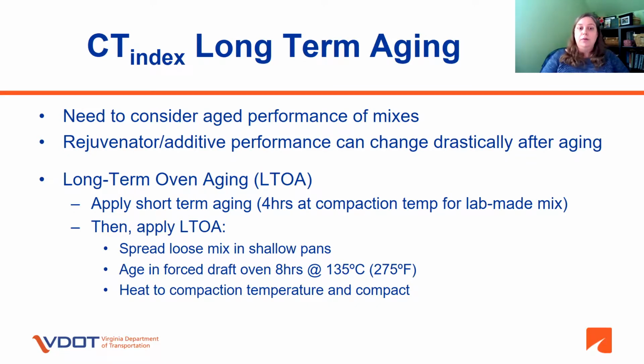After aging, rejuvenators and additives may significantly change your performance, and not in a good way. If a rejuvenator is not designed such that it continues to modify the mix correctly after aging, your cracking index could drop off drastically. The long-term oven aging is applied after 4 hours of short-term aging.